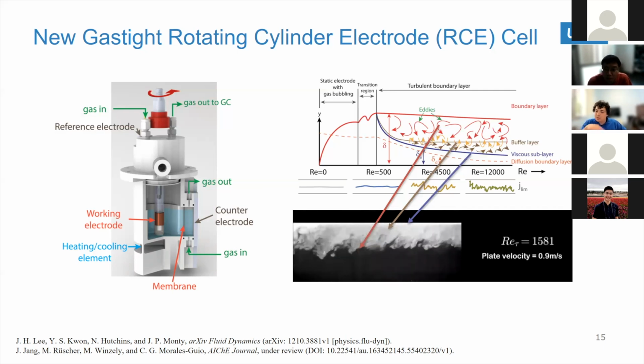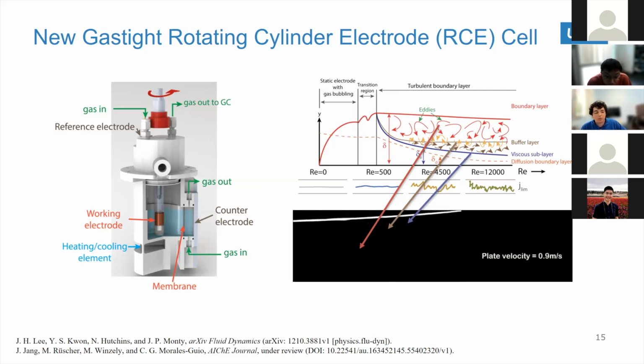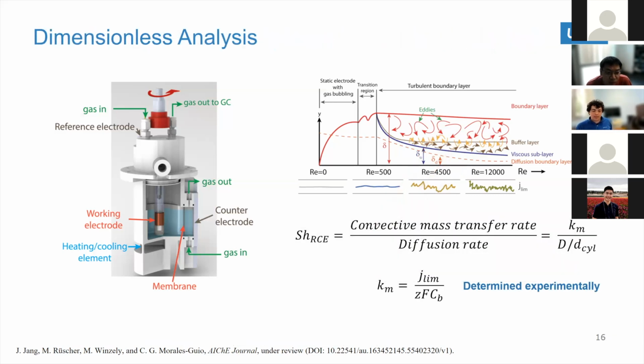We're creating some turbulence, we're creating some mass transport that goes in and out of the surface of the electrode that helps us bring reactants to the surface of the electrode, but also helps us remove reaction intermediates. So we characterize the mass transport properties. We don't need to actually model the complex hydrodynamics of the system, right? We can actually just experimentally measure the combined mass transport coefficient. So this will be the Km value.